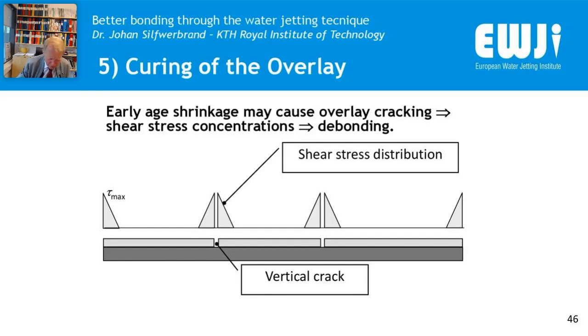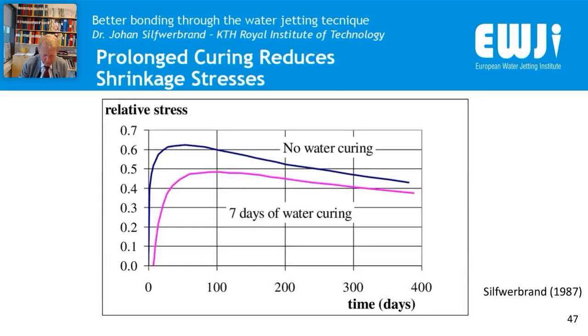I don't think this problem is that big, but in order to reduce the risk of this, you should cure your concrete properly. And here is a calculation example: if you have poor water curing, you will have stresses that are 0.6 times the tensile strength of your concrete. And if you have 7 days of water curing, you could reduce it to 0.5. So it is a clear difference.